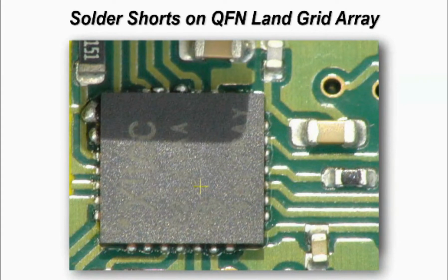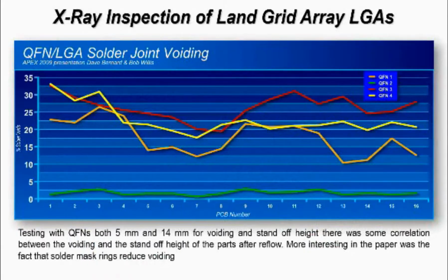And on this particular product that was being built, you can see solder shorts to the side. Now, you wouldn't generally expect to see solder shorts on pitches of this type. So there had to be something different other than poor placement, poor printing, etc. So doing some trials, we were able to establish what the root cause was. So try and look, not at the obvious; sometimes it's the less obvious that causes some of the problems in manufacture.